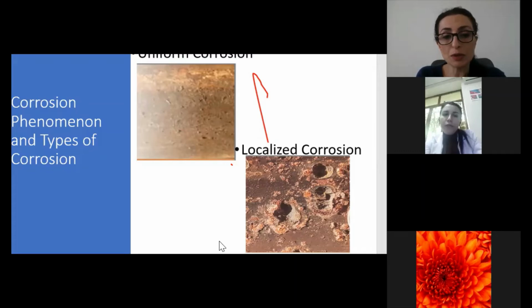Uniform or general corrosion is a metal loss that proceeds more or less evenly over the surface of metal or a large fraction of material. During uniform corrosion, local anodes and cathodes don't become fixed. This form of corrosion can be identified by visual examination of the metal surface, and it's recognized by an overall roughening of the surface. Because uniform corrosion occurs over a large area, it's more easily detected from outside of the pipe using ultrasonic measurements than isolated fittings.